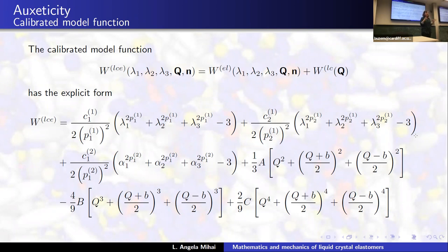So people, when they produce auxetic material, they produce them from structural architecture. They have that kind of hinge structure where you stretch a material and then, like in umbrellas, they become wider. But this is a material which exhibits auxeticity at molecular level. This is very new and it's fascinating, but needs a bit more work.